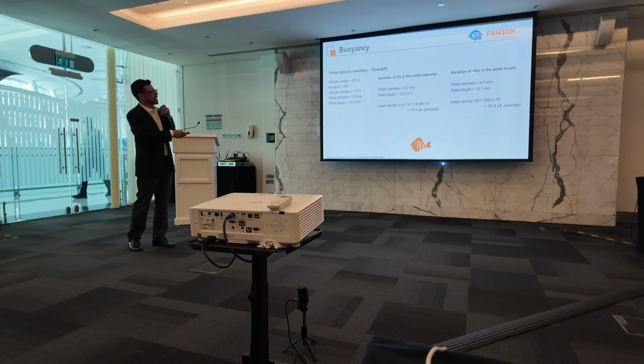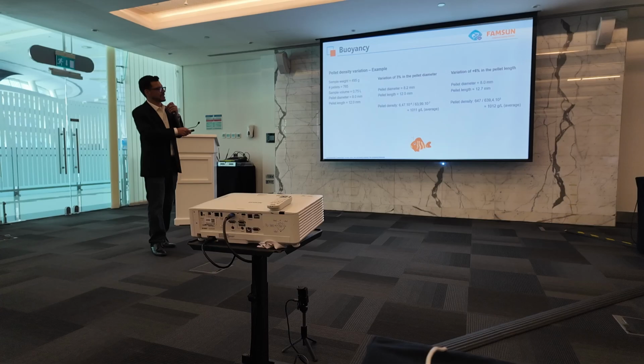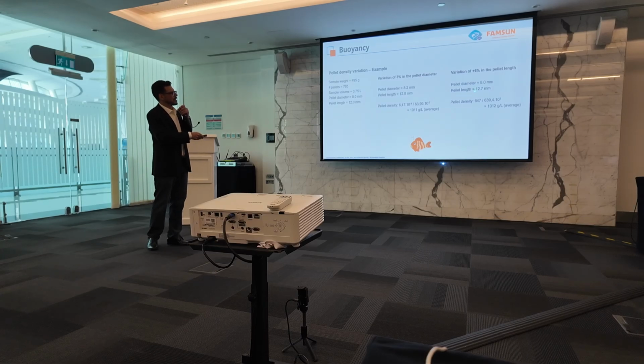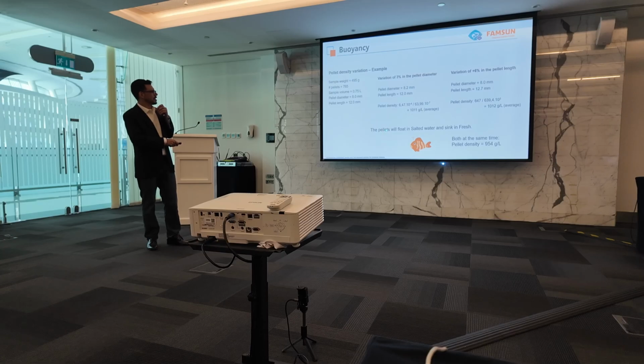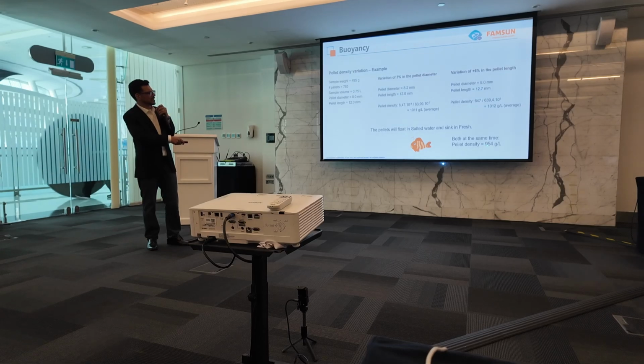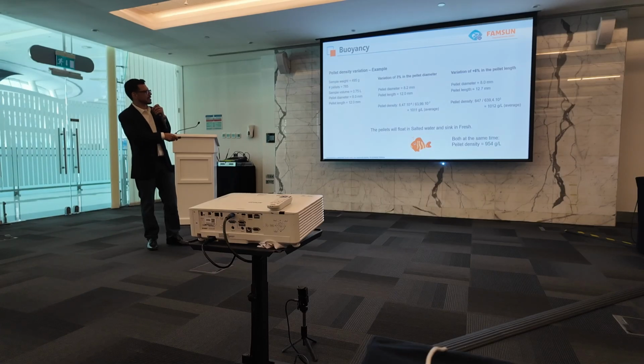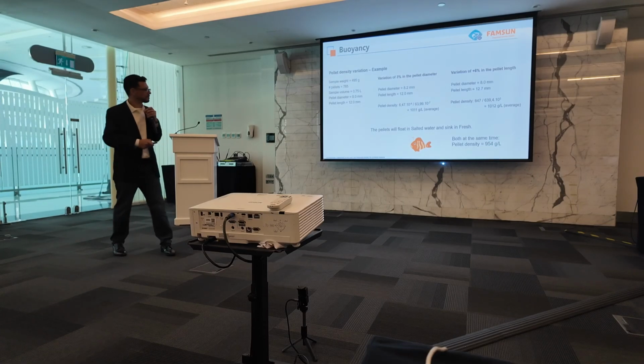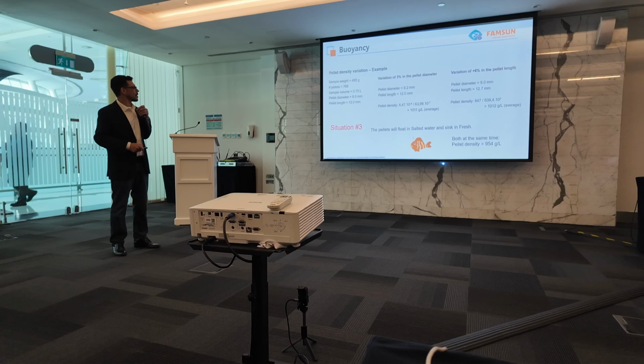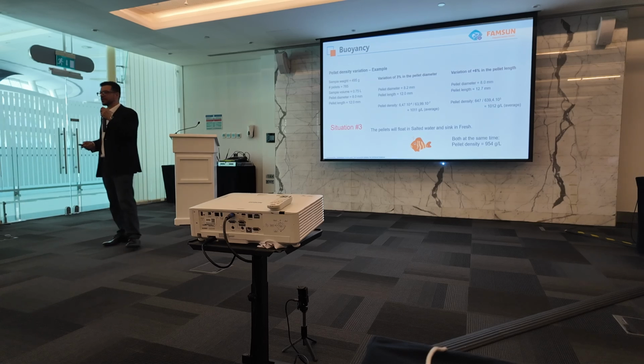If I have a variation of 6% in the pellet length, which is usual as the knife wears out, then now we have a little bit larger pellet length, and when we calculate, we have a similar average pellet density. So what's the conclusion? These pellets will float in salted water and sink in fresh. And if these two variations apply at the same time, then the resulting pellet density is even worse, is lighter, and would float in the two cases. This is how we explain situation 3.